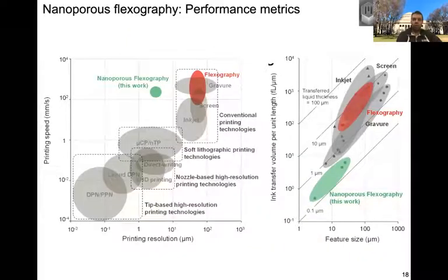And when it comes to where this process stands relative to what industry and academia have done, two charts here I think are important. The first is the idea of this work was to do printing at a feature resolution in the single-digit microns. And as of the first paper we had demonstrated a resolution of about 3 microns, the smallest feature we made. And to do that at a process speed that is commensurate with what industry needs.